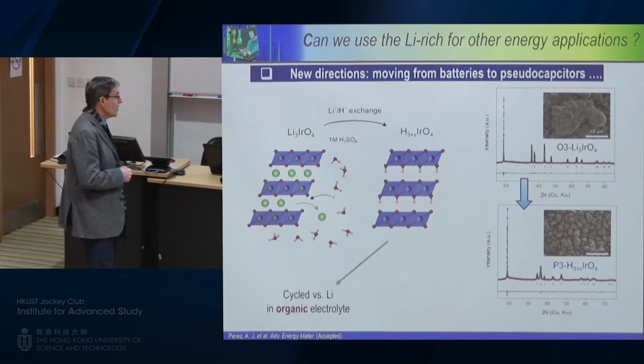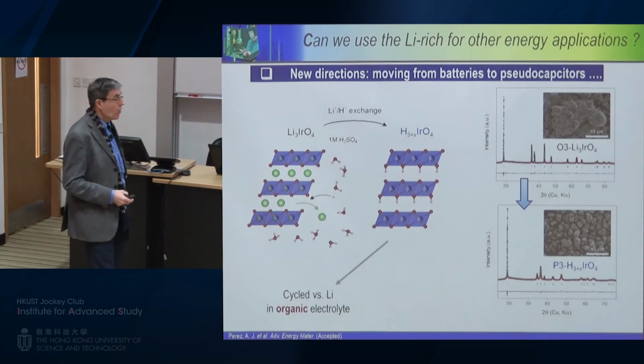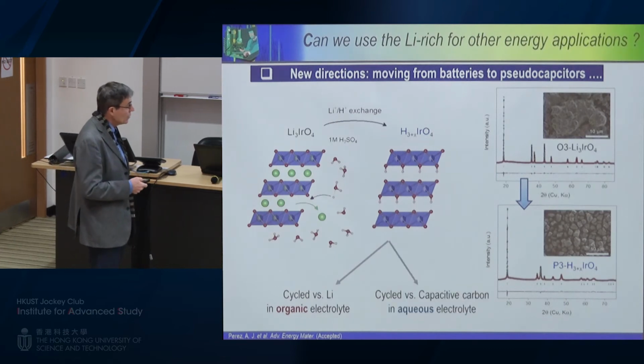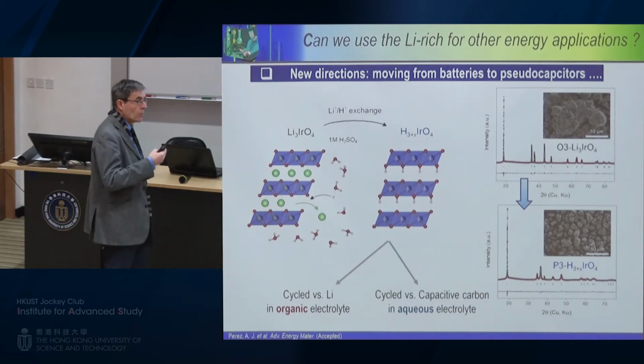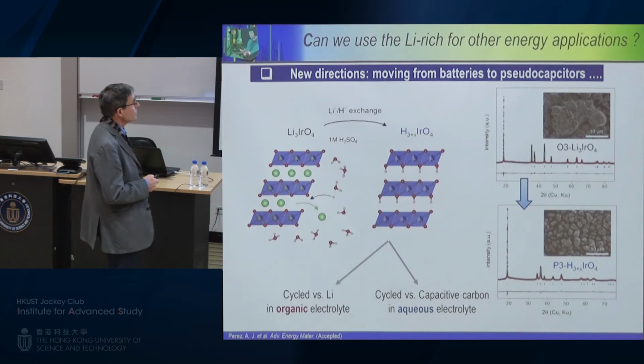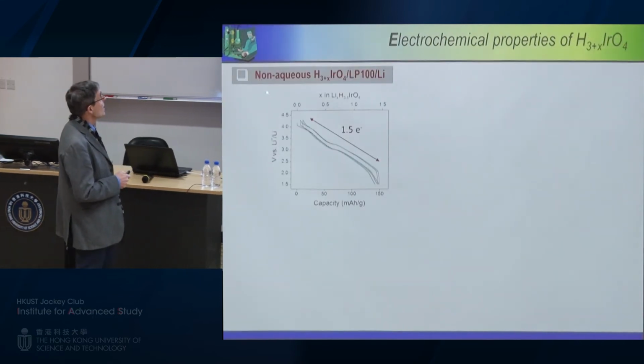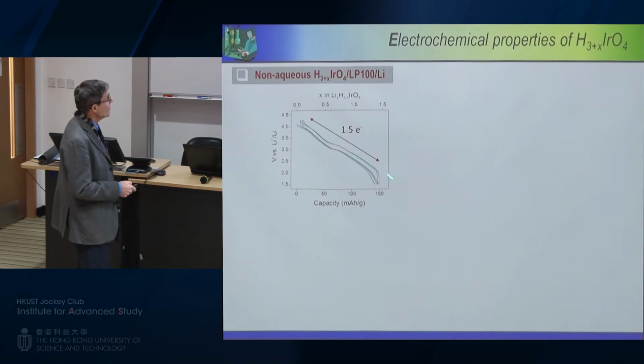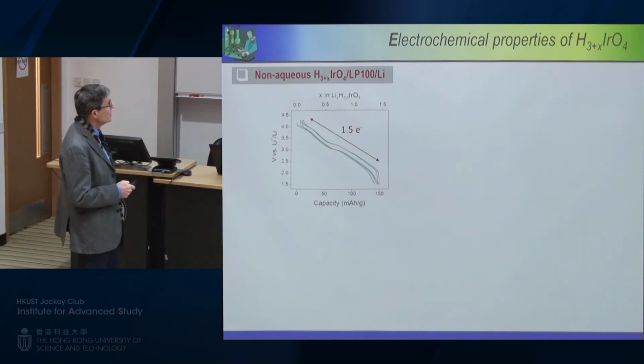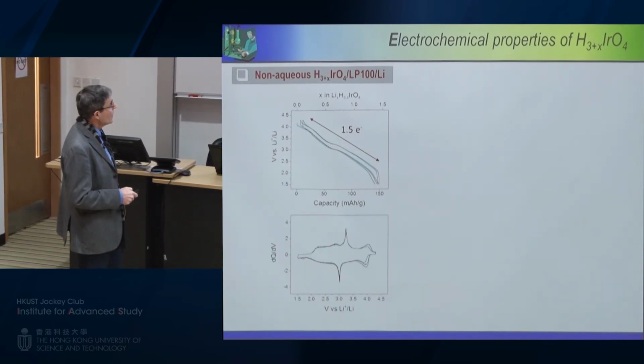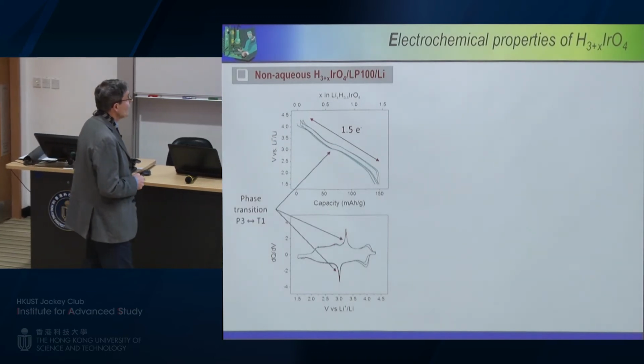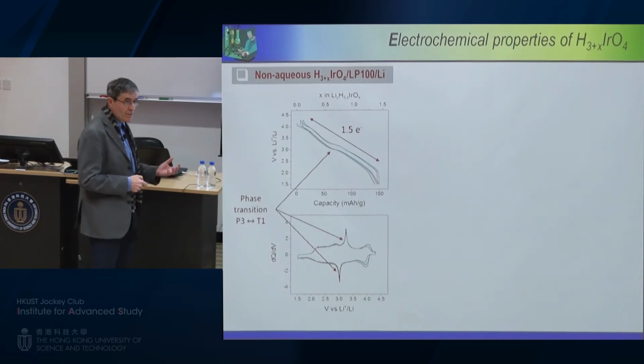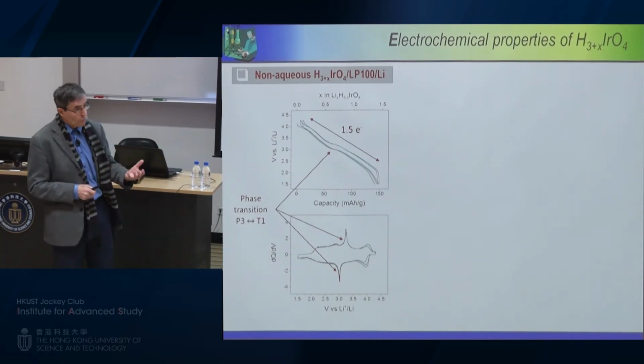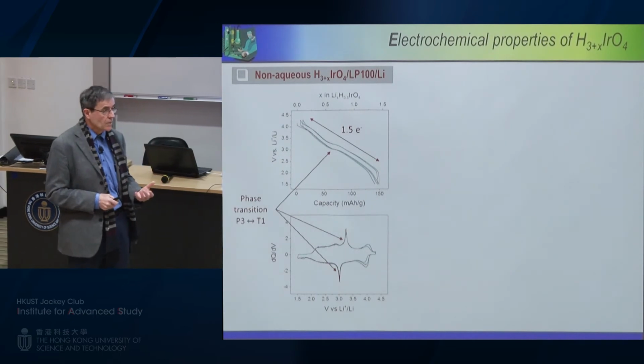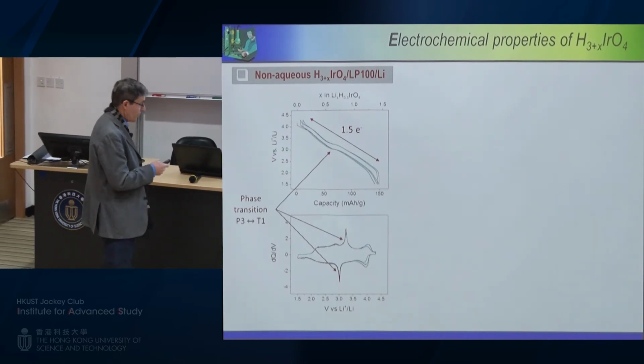of lithium, either in organic electrolyte or, what is new, an aqueous electrolyte, which means that now we are talking about protonic aqueous systems. Indeed, if you look now at the non-aqueous electrolyte, you have here the voltage composition curve with the derivative, in which you have a phase change as indicated here. Now you look at aqueous media, where in this case you are looking at protons, which are quite a bit faster than lithium. You expect to have, of course, a faster rate.